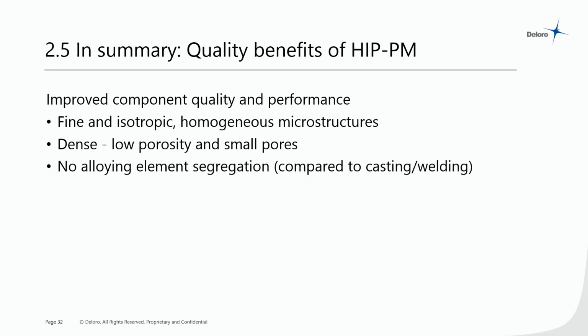So in summary, the quality benefits of HIP PM, not the cladding, but just the HIP PM where one makes a component from a powder, are that the component quality and performance are much better. So you have this homogeneous microstructure, you have a very low porosity and very small pores, which is absolutely crucial for fatigue and toughness. And there's also no alloying element segregation, which is the kind of thing you get mainly with casting, but also with welding.